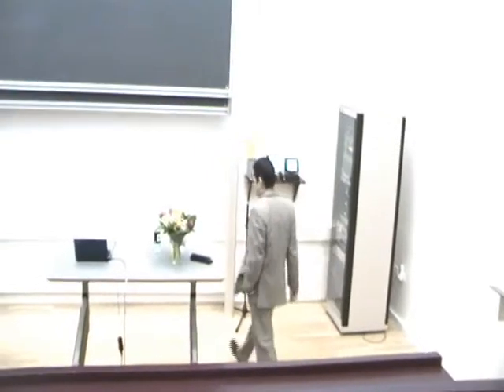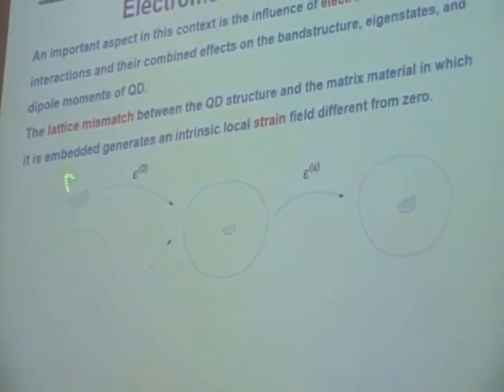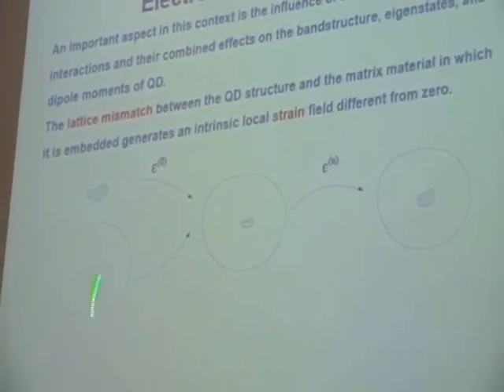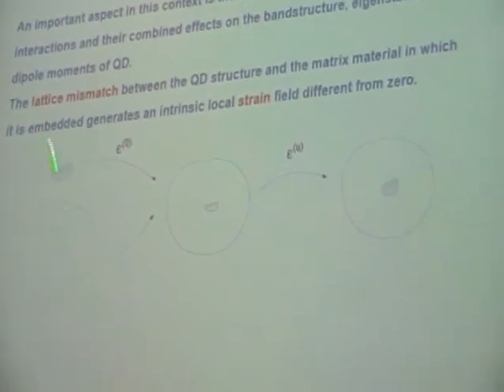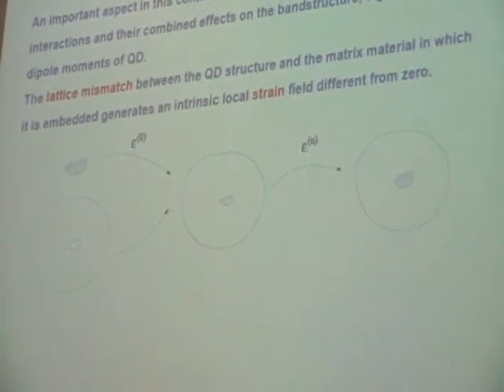Let's start with the modeling itself. One of the most important aspects in this context is the electromechanical strain field of the dots, and especially its influence on the optical and electronic properties. Here you have a picture — not a realistic representation of the dots, but a simplified model to help you understand why we have this mechanical strain field inside the dots. On the left you have two separate structures: the dot material and the matrix material in which we want to embed the dot. It's like inserting the dot inside a hole in the matrix.